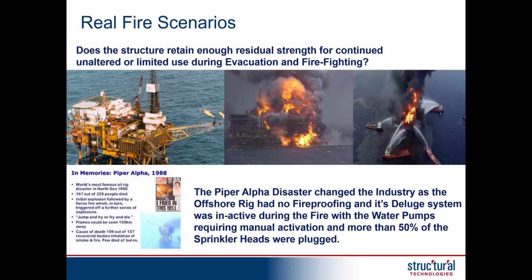And it was primarily due to inactive deluge systems that required activation, and most of the sprinkler heads were already plugged. And what made it very tragic is that most of the people that died ran to these BRBs, these blast-resistant buildings, which also have 3-hour fire ratings, and they waited inside those structures. Unfortunately, the fire lasted much longer than 3 hours, and most of the people died because of smoke inhalation, not from the burn. So it was very tragic. The ones that did survive actually jumped, and it was, stay and fry, or, jump and try. So those were the monikers.